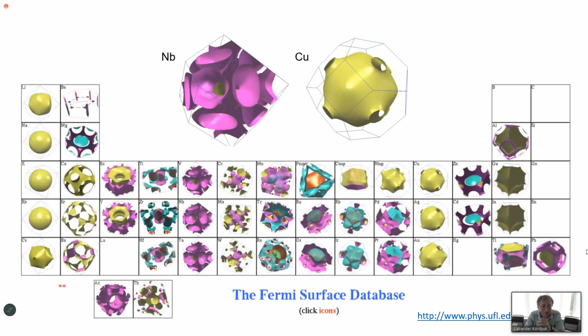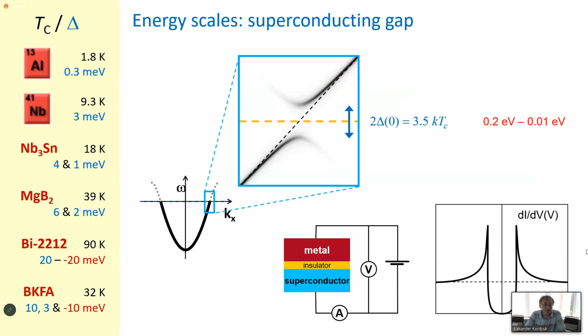these are the simplest situations, and even for simple crystalline structures of simple metals, such Fermi surfaces are only for a few metals, but usually the Fermi surface is a more complicated thing. And this is especially so for other materials. But a good thing about it is that the most interesting materials for physics are quasi 2-dimensional, and therefore we have this possibility to consider band structure as surfaces, and actually the electronic band structure, spectra or spectral function, or this electronic structure, as I call it, we consider as a field in 3-dimensional space where you have two momenta and energy.